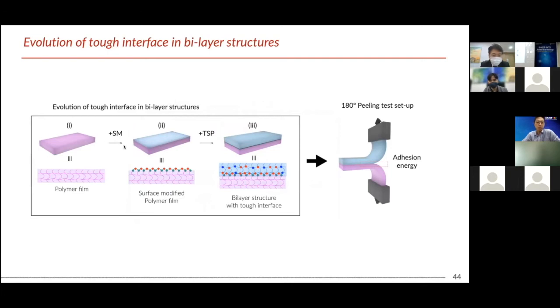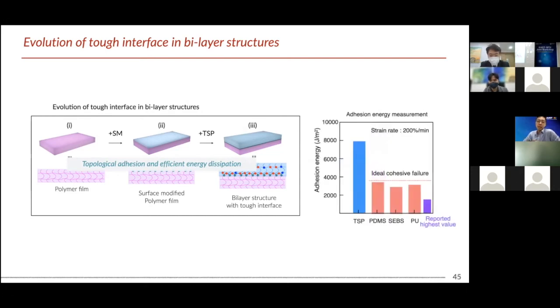So based on the surface modifier, I fully change the surface properties of the polymer film, and these modified surface properties are identical to the secondary polymer. And because of the very nice hydrogen bonding interaction, the secondary polymers start to stitch into this surface and induce this nice bilayer structure with the tough interface. So the basic principle is the topological adhesion and also the efficient energy dissipation by the self-healing polymer. So we can make a really nice tough interface between various polymer surfaces.